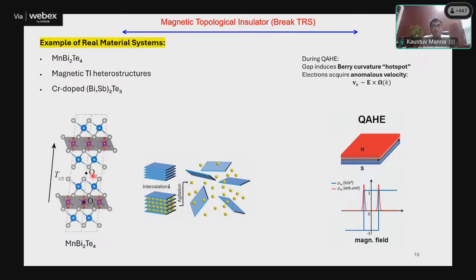There are even reports showing that if you make MnBi2Te4 with 1, 3, 7, 9, like an odd number of layers, you get one property, because one MnTe layer will be kicked out. Whereas if you make 2, 4, 6, 8, an even number of layers, your property is different. The property of this compound is so precisely controllable.